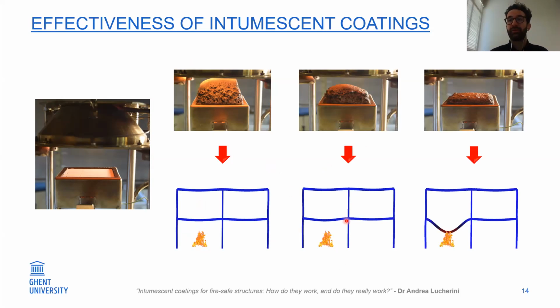And this is the case when you have the coating that is swelled less and you have like a poor insulating performance, and the steel beam will deflect much more. And this is very important when you do structural assessment of your structural system when it's exposed to fire.